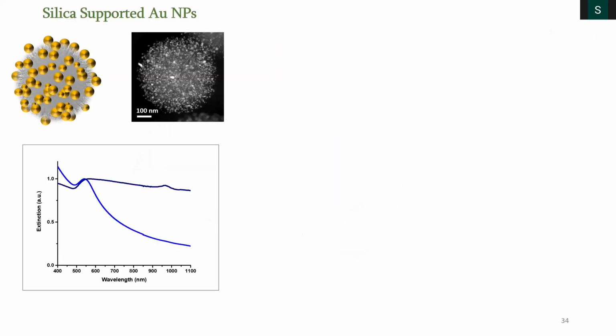The only problem with these systems is, if I take a silica and load it with gold nanoparticles, the light absorption is like this, the blue curve, around 550 nanometer. But if you really want a sustainable process with a very good yield, then you need to prepare a material which should absorb the entire visible and even near-IR light, something like a broadband light absorption. How do I achieve that? How do I achieve a broadband light absorption?